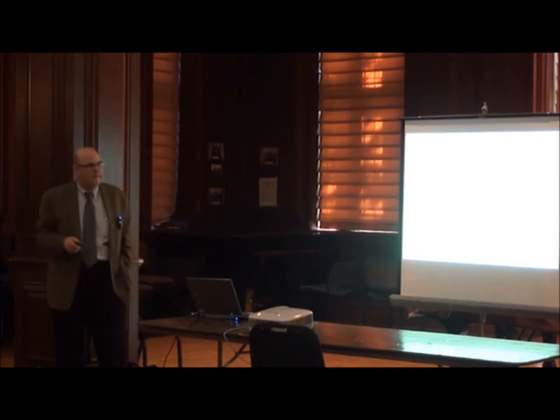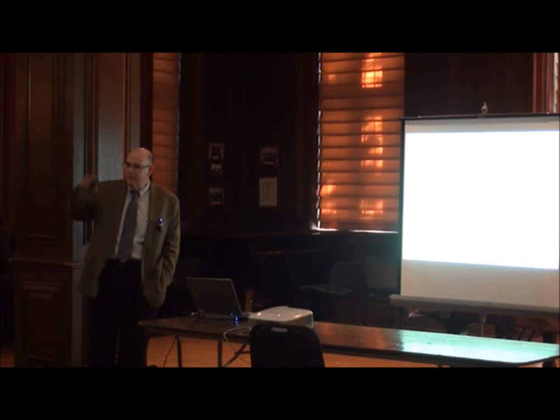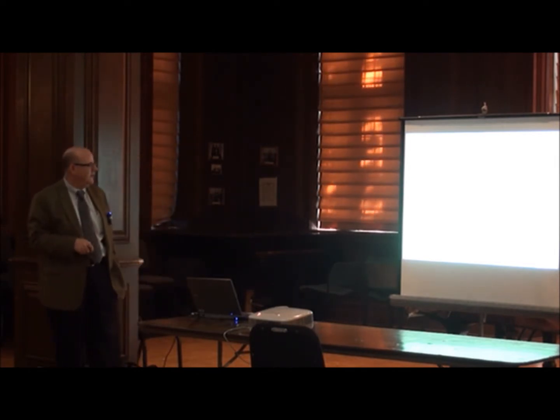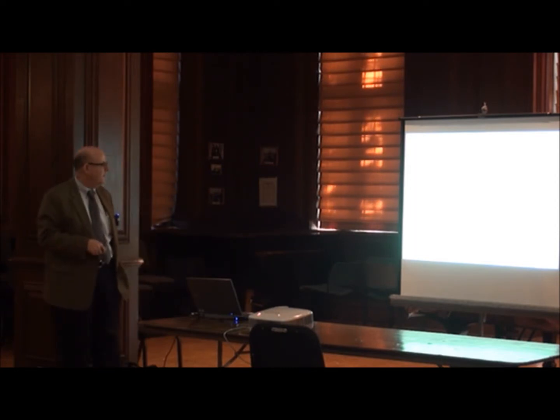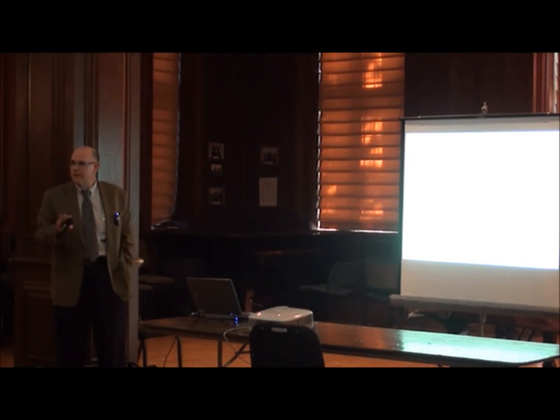And if we let the spheres move around and say they're randomly distributed, what do I find out? And they did this whole general theory of random distribution of spheres. So they had the more general theory. And said that, hey, if you use an exponential distribution, you actually get an interesting result. You get the result that the real area of contact under elastic deformation is indeed proportional to the load linearly. So it's independent of any kind of exponent here. And it's inversely proportional to the modulus. This sort of stuff makes sense.